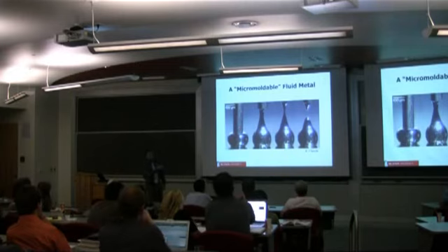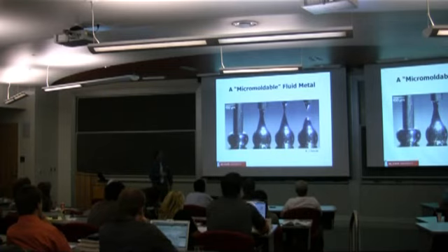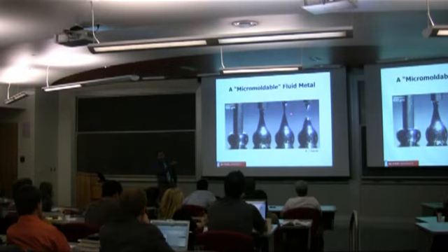And there's a couple things that I want to point out. First is that the metal sticks to the substrate, which is not all that unusual. There are other liquids that stick to the surfaces, but mercury would not necessarily do this. And the other thing is, as you stretch it, it sort of breaks like bubble gum. And when it breaks, it actually bifurcates. It forms two cone-shaped structures. So this image is not just captured in time. This is the stable structure that forms with this metal.